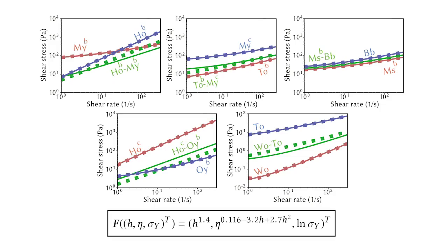Based on a data-driven approach, with a variety of materials covering different types of rheological properties — including polymers, suspensions, and those nearly Newtonian — we arrived at a model that has a good qualitative match in the behaviour of effective viscosity for more than two orders of magnitude variation in the shear rate.